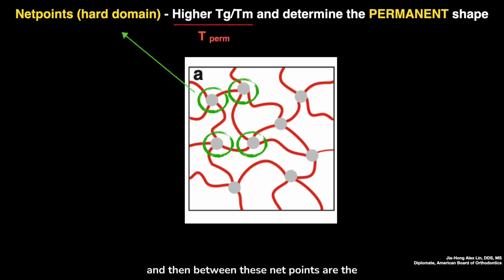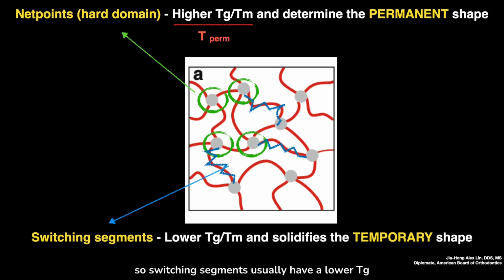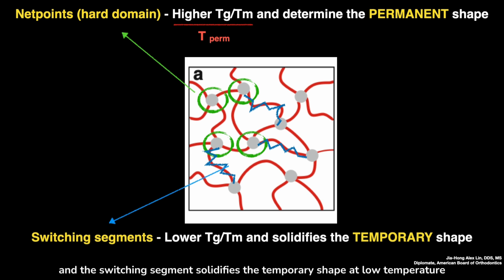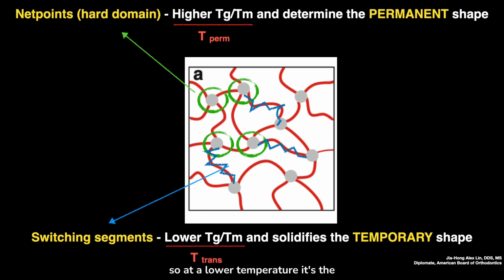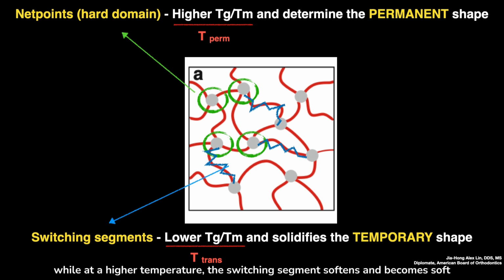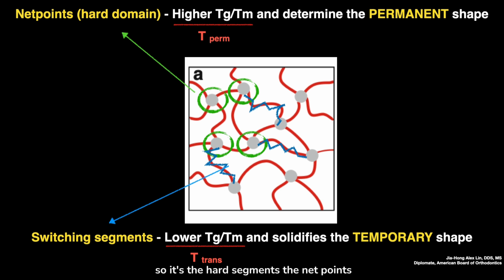And then between these net points are the blue zigzags that we call switching segments. Switching segments usually have a lower TG, and the switching segment solidifies the temporary shape at low temperature. So at a lower temperature, it's the switching segments that hold the shape of the aligner, while at a higher temperature, the switching segment softens and becomes soft, so it's the hard segments, the net points, that hold the shape of the aligner. The special thing about switching segments is that they're sensitive to external stimulus.